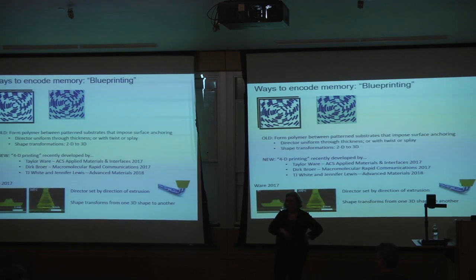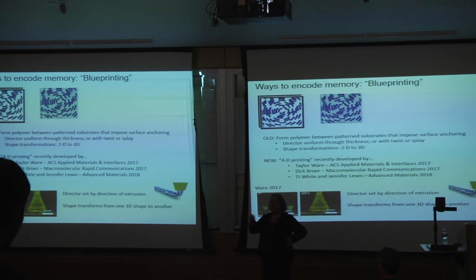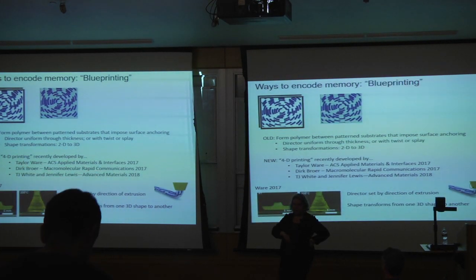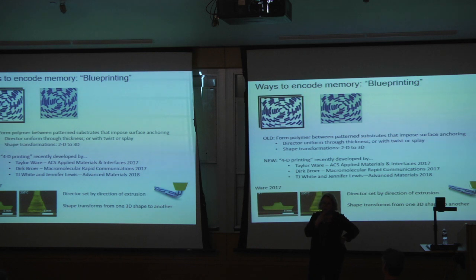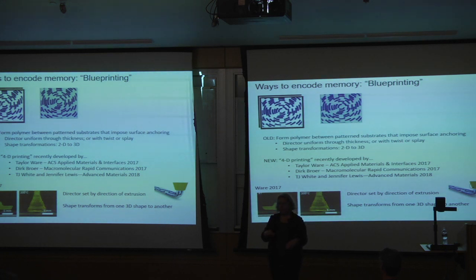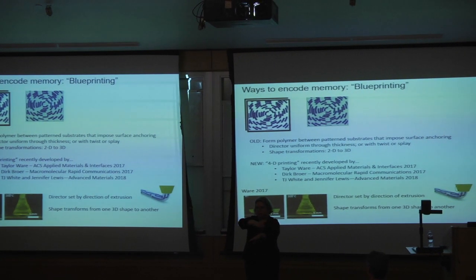4D printing is when your 3D printed object changes shape after you build it. And I was introduced to that concept by Sabeta Matsumoto, who was a postdoc at Harvard working with the Lewis group, and she figured out a way to print. It wasn't actually a liquid crystal polymer. It was a clay composite that had cellulose fibers in it. And when you put the material down, the fibers would align with the extrusion direction, like parallel to when you put the toothpaste out, right?